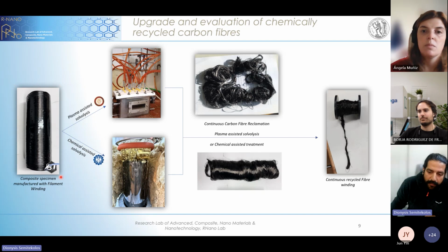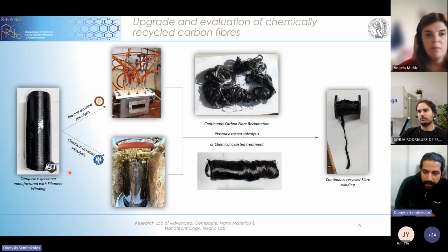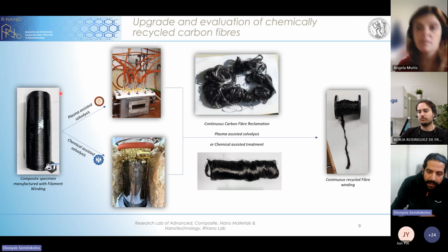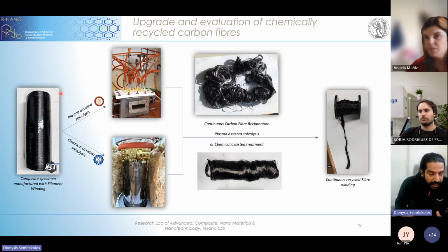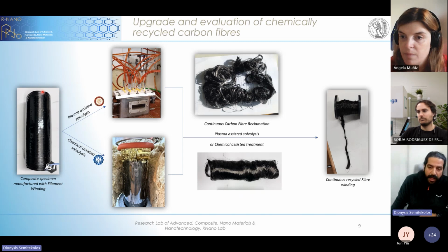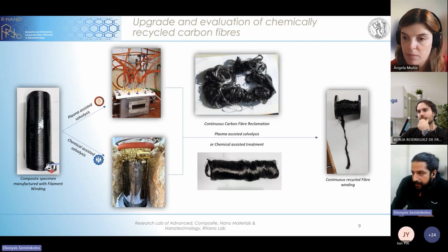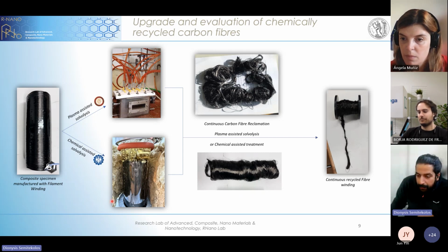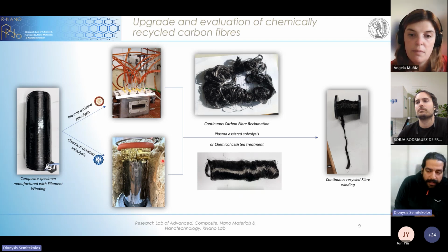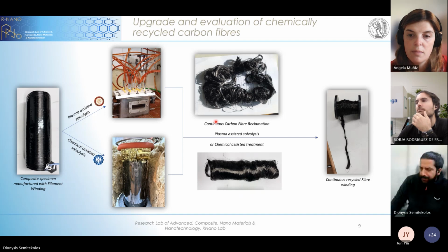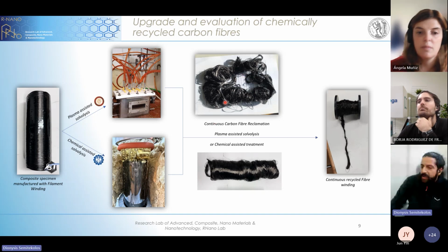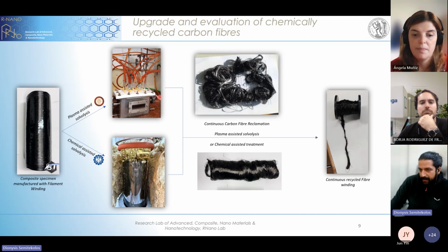We all start from these tubular specimens that come from BT Composites in Florina, and they are produced with filament winding. These parts are made out of continuous fiber, so there are no cuts. They are specifically designed to have carbon fibers continuous from one point to the other. So the idea is to use this plasma reactor and this ambient conditions reactor, using different solvents. For example, in plasma we have nitric acid, and here we have polyethylene glycol as solvents to reclaim continuous carbon fibers. Here you see how the parts look after the retrieval from the reactors.